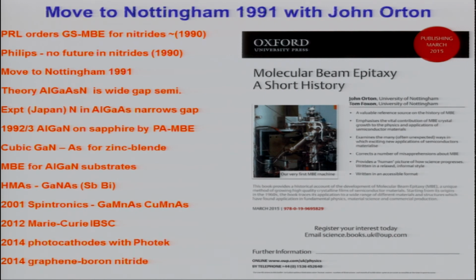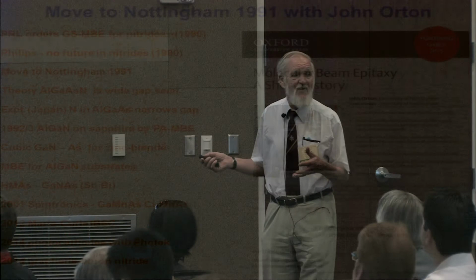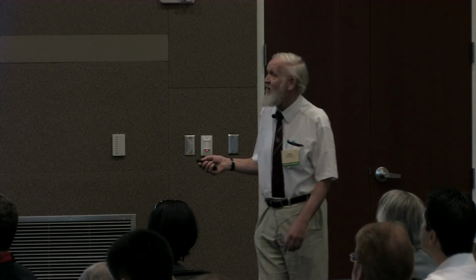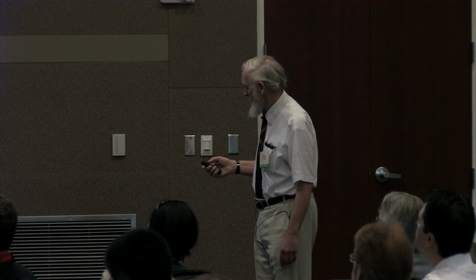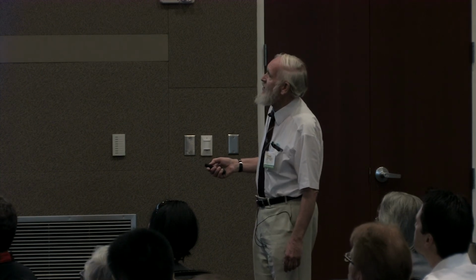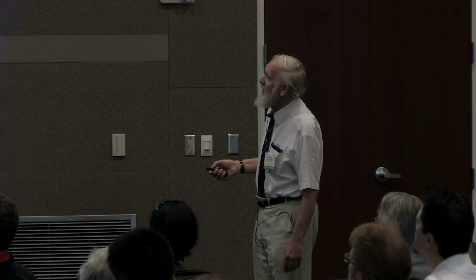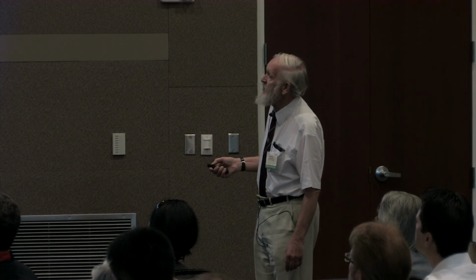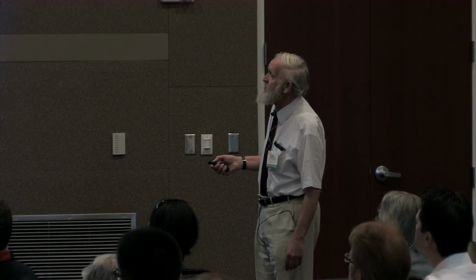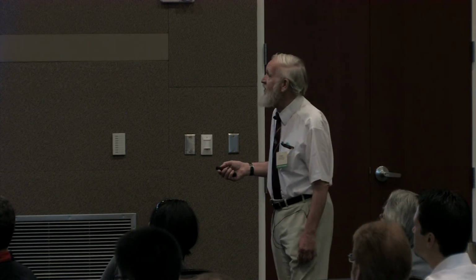So we moved to Nottingham, and the original intention was to grow aluminium gallium arsenide nitride as a wide bandgap semiconductor, because that's what the theorists told us at the time. Of course, it didn't work out like that because, again, being an international effort, experiments in Japan show that if you put nitrogen into GaAs, it actually narrows the gap. So that idea was dead.